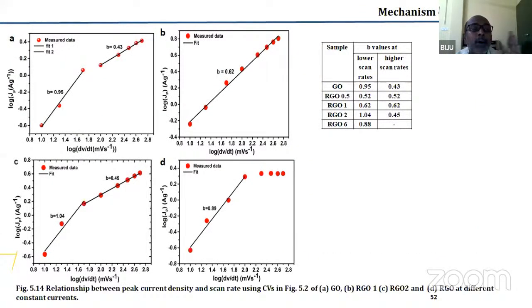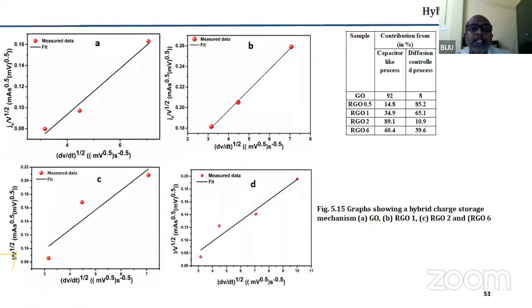Then the mechanism in all these cases was studied, and it was found that in that particular sample, at all the scan rates, intercalation was happening, but for the other samples, intercalation was there only at the higher scan rates, whereas at lower scan rates, the surface-based mechanisms like double layer and pseudocapacitance were the dominating factors.